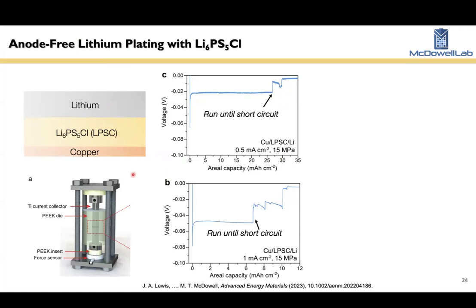They're very tricky to handle, and you have to have everything very precisely controlled in terms of the uniformity of the different layers, the height differences on the current collectors and the rods here in these sorts of cells, and also the pressure distribution across the cells. So we're running these at 15 megapascal stack pressure. But basically what we found is, by a series of optimization steps and cell design steps, we were able to get very good performance in terms of lithium deposition.